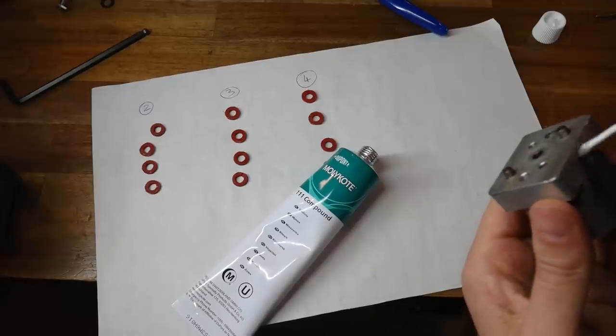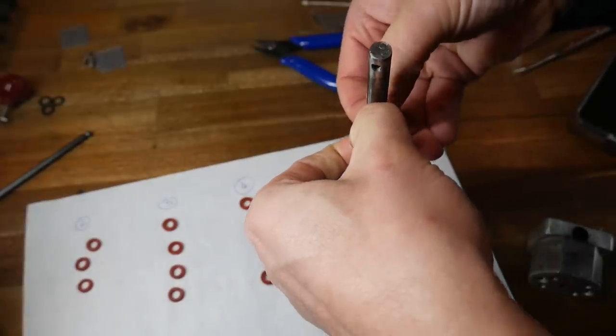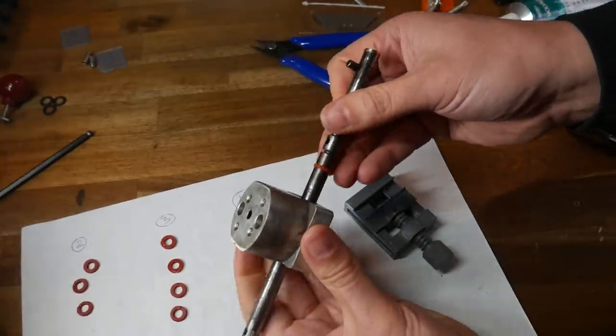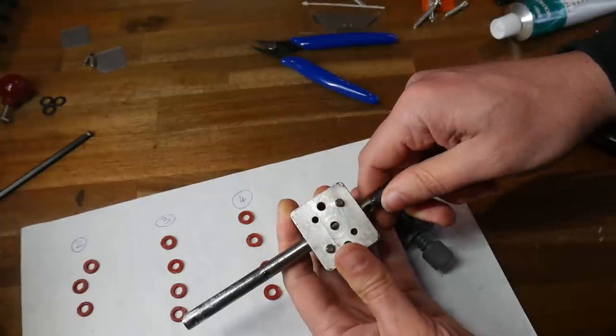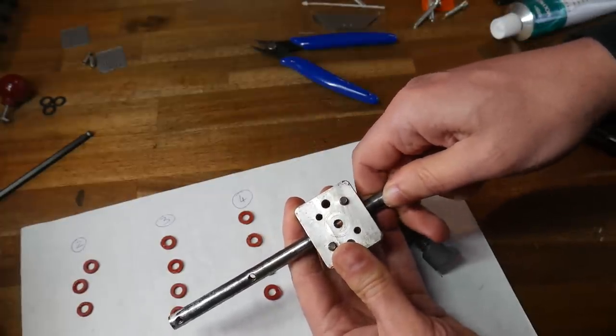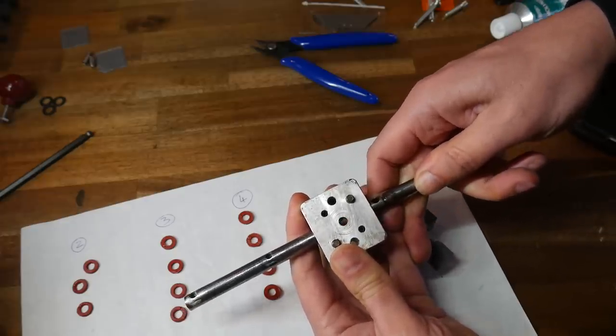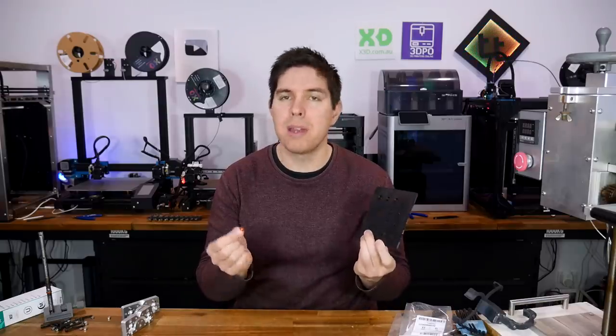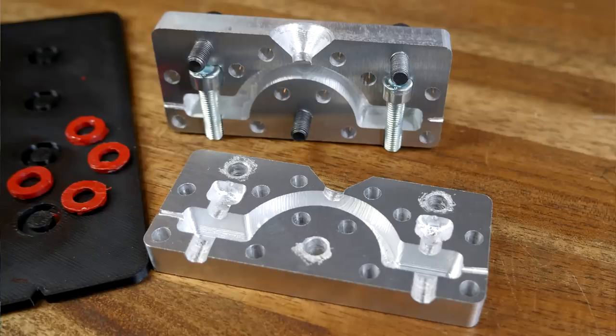I got out my fancy lubricant, and applied it to the inside of the injection molder bore. And slid down the smaller silicone washer into place on the valve rod. And annoyingly, I soon ran into the same problem as the oversized o-rings. When installed on the rod, the diameter had changed, to the point where it was a tight squeeze, and I could force it through. However, with that came consequences. As I tested the movement, I could see that it was being torn up by the hole, because it was just too squishy in there. So because of the clearances being wrong, there was no way that my silicone washer was going to last. There's just too much damage from all of that rubbing. Frustratingly, I think it's going to take a fair bit more time to cast variations until I get the size just right. I just got to be patient. But don't worry, I did get another part of the project finished. So let's inspect this plastic mold.